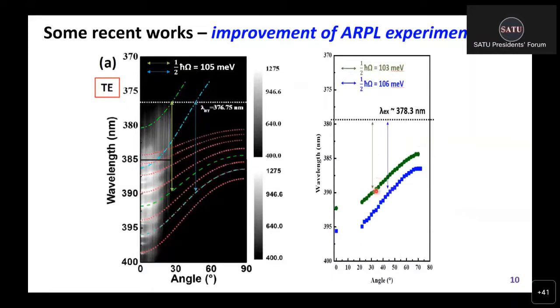So you can see the anti-crossing features occurs around the 30 to 45 degrees. Anti-crossing points is around here. These degrees are very similar with the prediction of the red dashed line here. So this also implies the methodology proposed here to calculate the index dispersion is accurate.